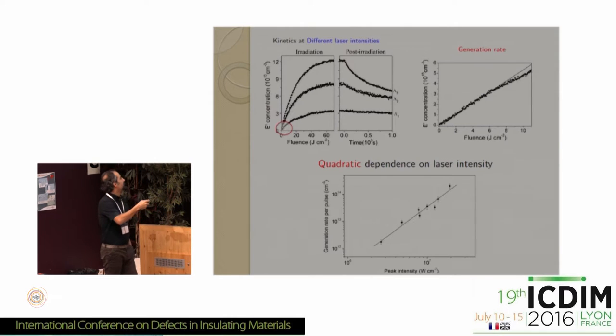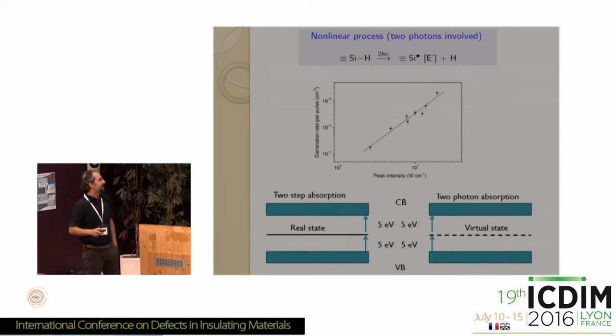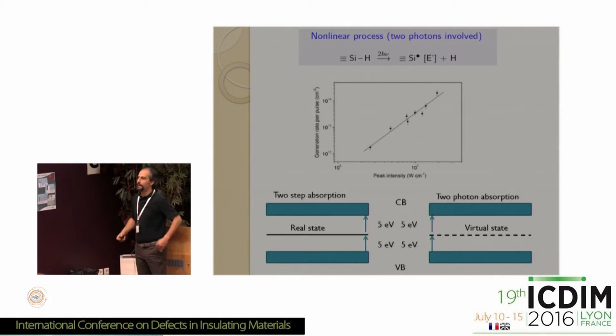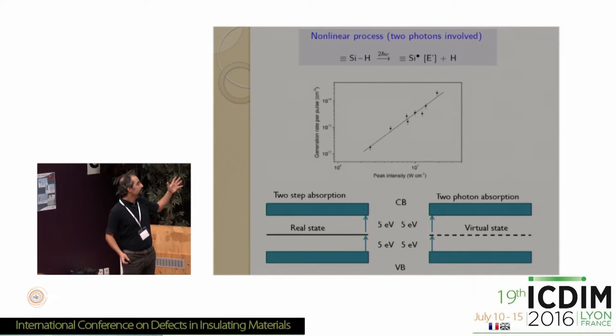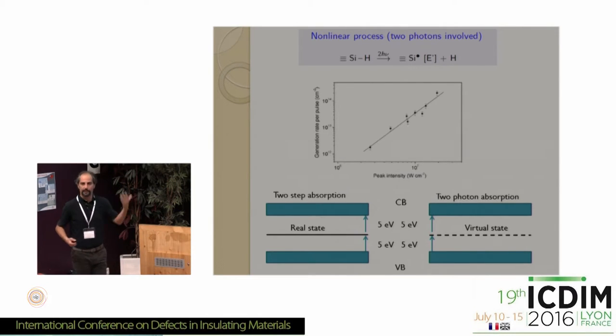Precisely, the defect generation rate is linearly correlated to the square of laser intensity. There is a quadratic dependence, as you can see in this plot. Now, this means, essentially, that two photons from the laser field are used to generate the defects by photochemical breaking of SiH bonds. The fact that two photons are needed is not surprising, because if the band gap of silica is about 10 eV, and we are using a laser whose photon energy is about 5 eV, of course you need two photons to overcome the band gap.